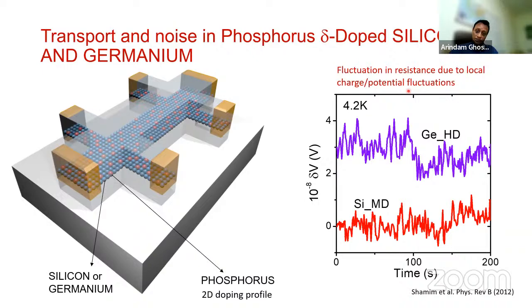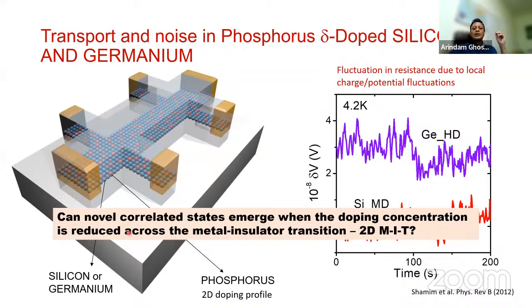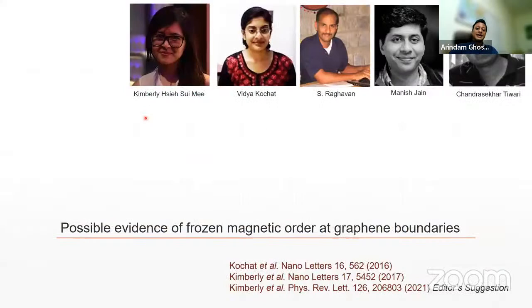It's one of the lowest noise two-dimensional systems that we have ever measured. The question we asked is: can correlated states emerge when the doping concentration is reduced across the metal-insulator transition? Which means when I start changing the concentration of this red color dopant, phosphorus, the system at some point becomes metal at high doping concentration, goes to the insulating side at low doping concentration, and whether there are correlated states or something interesting in that situation. So that was the question we asked with doped silicon. The reason I clubbed them together is that their experimental signatures were very similar.